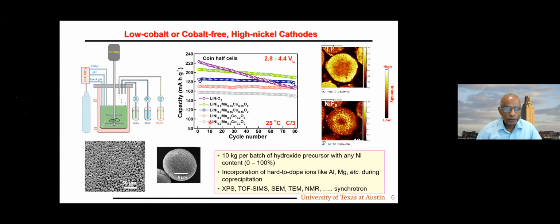Before I go into the details, I would like to mention 3 things. One is we make our own material. We can make any particle size of secondary particles, but normally we use 12 micron secondary particle size. We can scale up the hydroxide precursor in my lab, 10 kilograms per batch. And then we also make pouch cells. Then we have graphite. Lithium also we do to some extent.